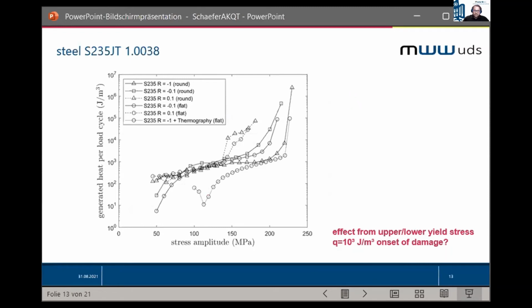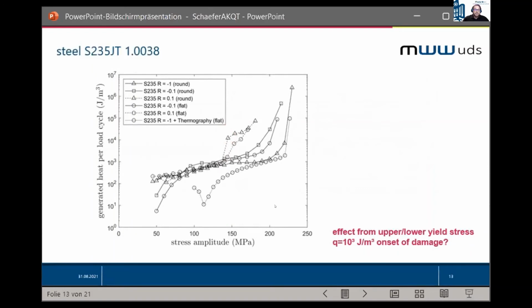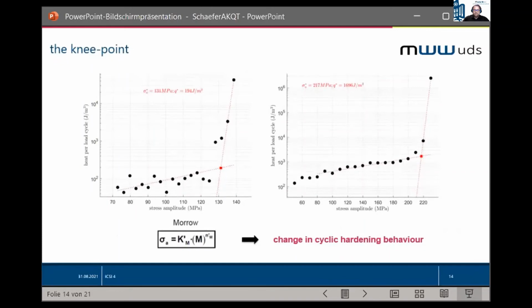If we now consider a standard steel, we see that depending on the R ratio of the test, the stress amplitude at the knee point evolves as expected, and we can see an effect of the upper and lower yield point for the R 0.1 sample, resulting in a step in the Q curve here at the knee point. And this gives a clear evidence of the immediately starting dislocation mobility when the upper yield point is reached. So the knee point characterizes a change in the cyclic hardening behavior. That's what the knee point tells us, and we can express a fit to both curves by the Morrow equation, and then we see that the knee point is simply a change in the coefficient of the cyclic hardening behavior.